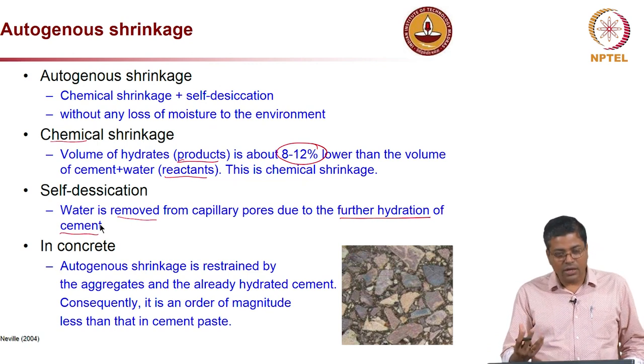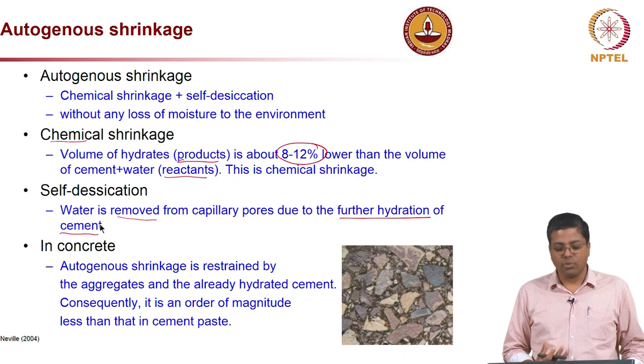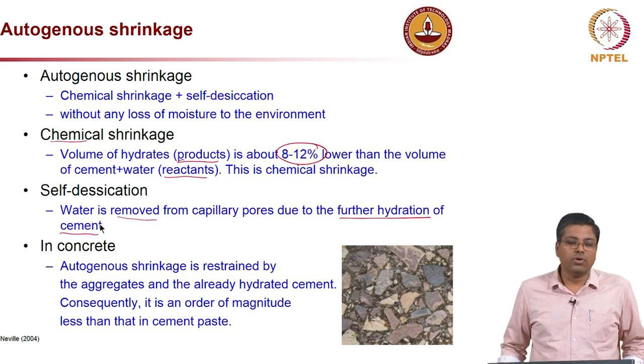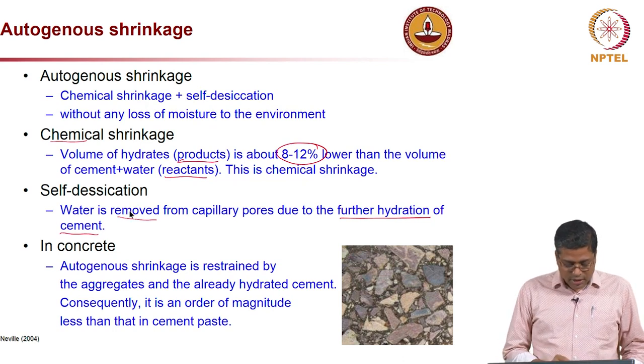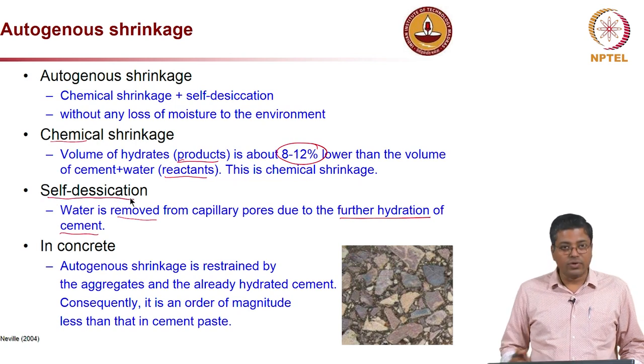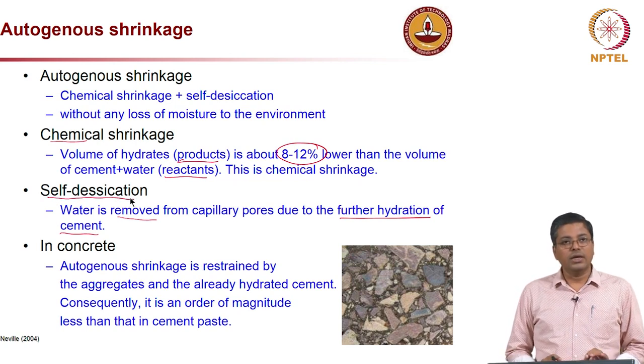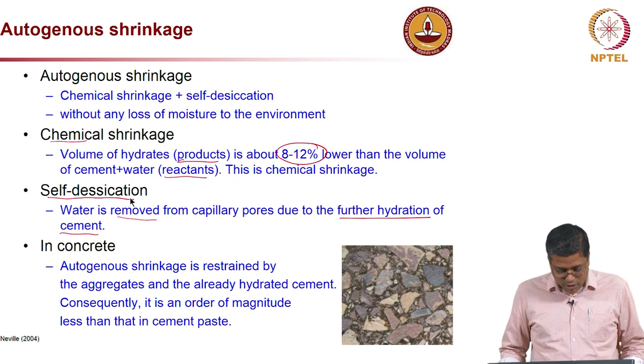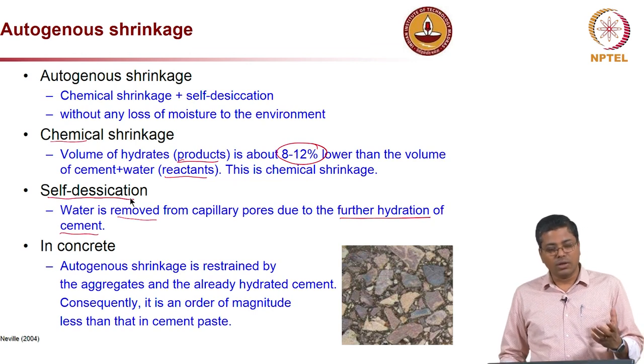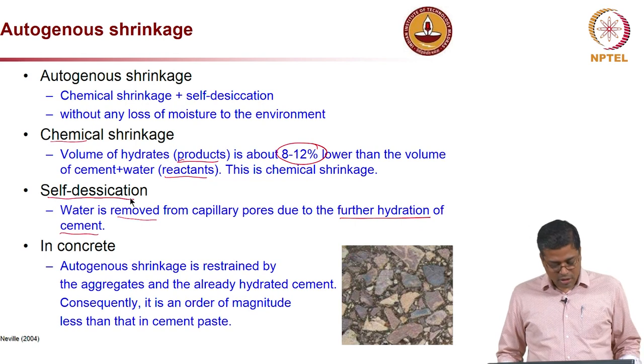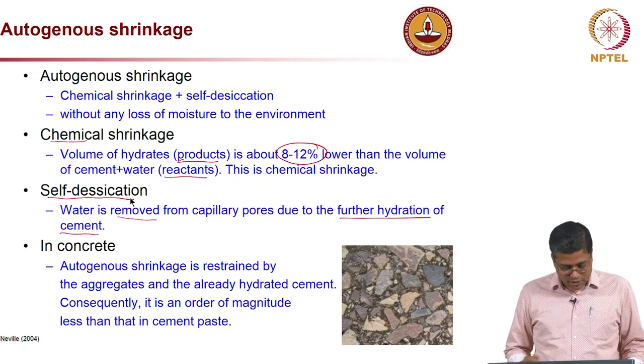So the water which is present in the capillary pores is also used for this hydration purpose, and that leads to something called self desiccation. And here very clearly water is not lost to the environment, the water from the pores is used for further hydration of the cement paste.